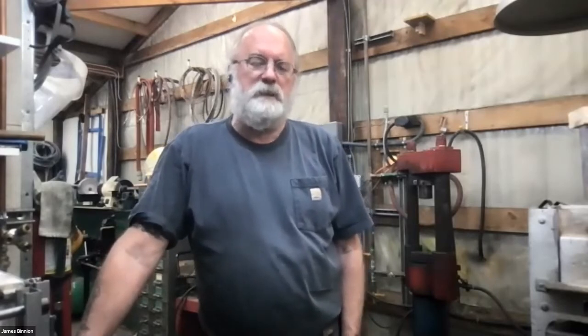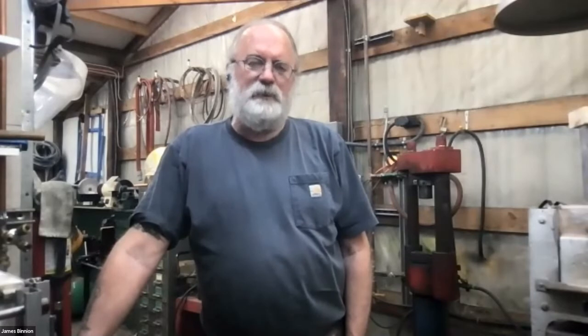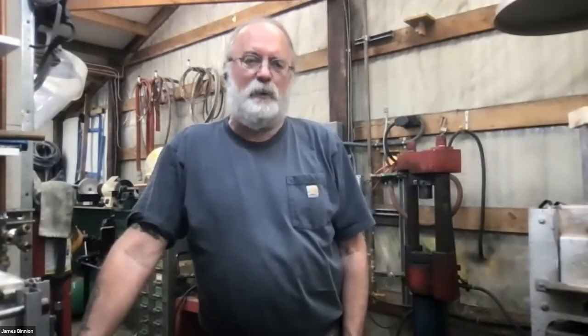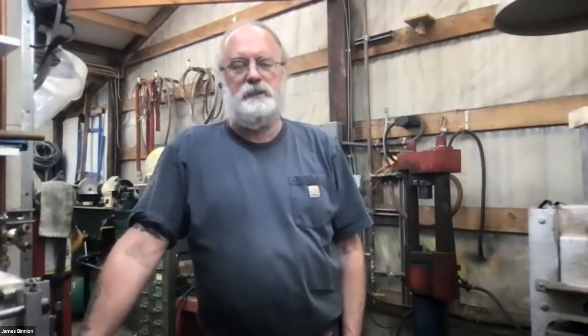When you're talking about a 1/4 inch or a 3/8 inch diameter piece of copper brass or copper silver, it loses heat so quickly that you can't get it twisted very well in time hot. And if you're sitting there trying to balance a torch and the twisting apparatus, your vise, whatever you're using to hold everything, it just gets to be too much of a crazy dance. And what I found happened is it's just way too easy to overheat the material and break it.